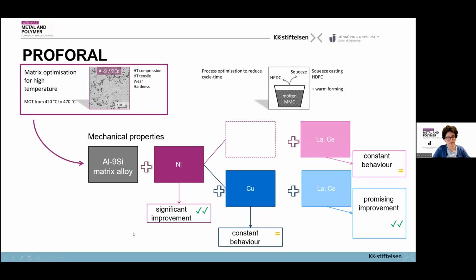If we look at the mechanical properties, we were very satisfied with the different results that we could see. Nickel really gave a significant improvement of the mechanical properties at room and elevated temperature, up to 470 degrees. The copper addition after nickel kept that improvement constant, but without an additional reinforcing effect. Lanthanum and cerium instead showed a promising improvement even when combined with both copper and nickel. So these results are very promising from the mechanical point of view, but then we also took care of wear and thermophysical properties to be sure that we weren't sacrificing those aspects, because they are still critical properties for the brake disc application, as Samuel presented.